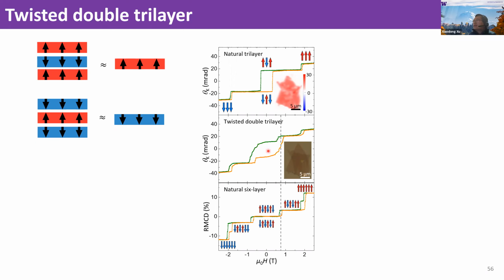So you can see that for the twisted trilayer, first of all, it resembles signals from these natural six layers. See, we have a little bump here. It also has a signal resembling six layers and trilayers, like kinks here and here, and a little signal with a non-vanishing hysteretic loop in the middle.